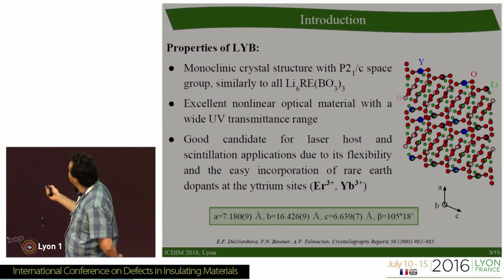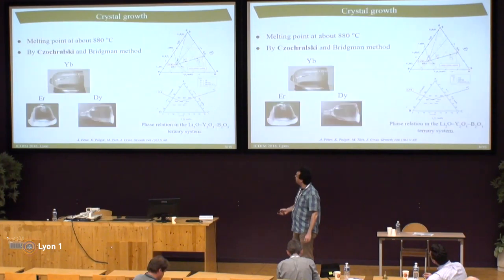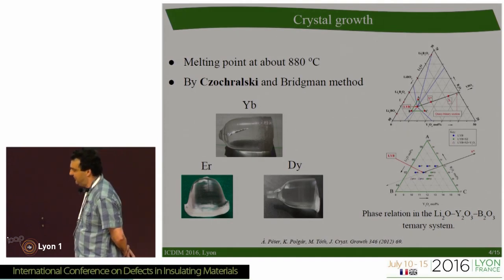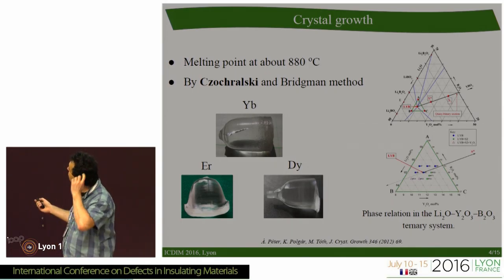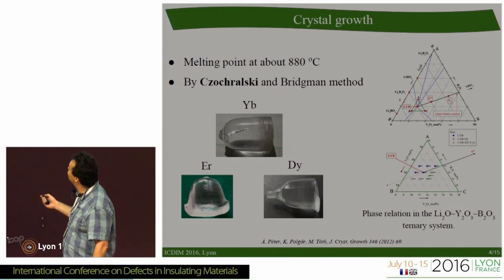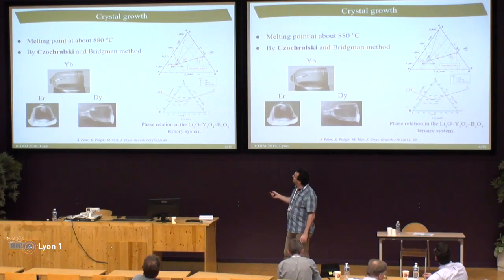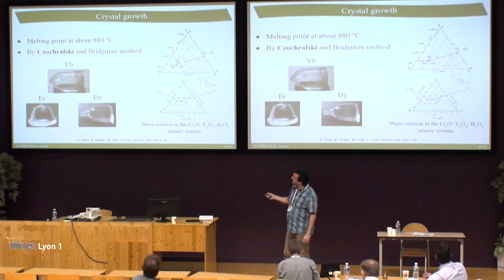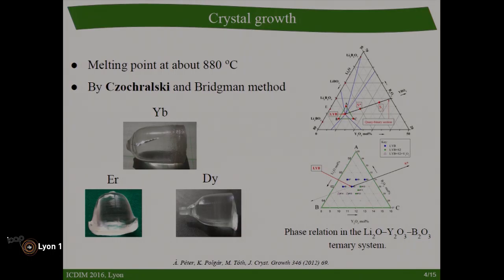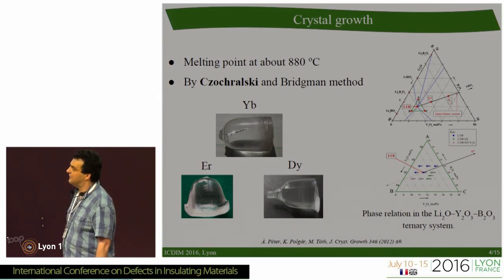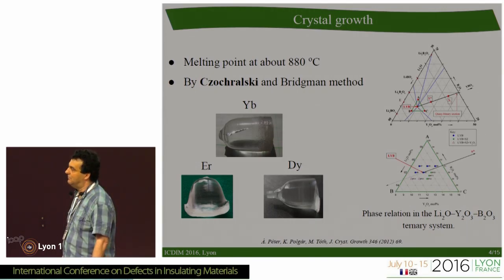The crystal structure shows a B direction which is a two-fold axis. Our department worked on the growth of lithium yttrium borate and determined the phase diagram — the area where we can grow the crystal. We then incorporated rare earth ions and obtained very good quality optical crystals. We used different concentrations and verified them by chemical analysis, confirming that the rare earth ions go into the crystal.